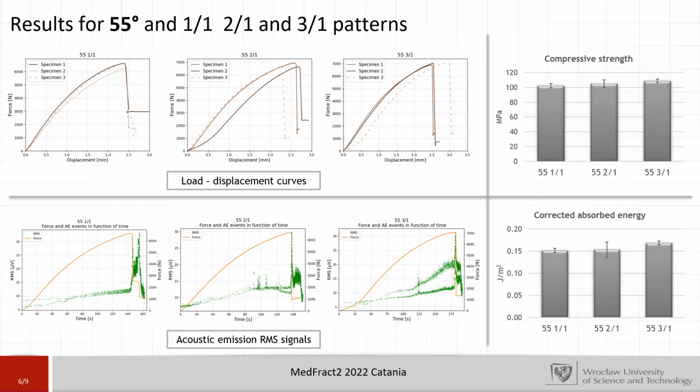To compare those different mosaic patterns, we didn't actually see huge, statistically significant differences in the compressive strength and absorbed energy between the mosaic patterns for this winding angle.